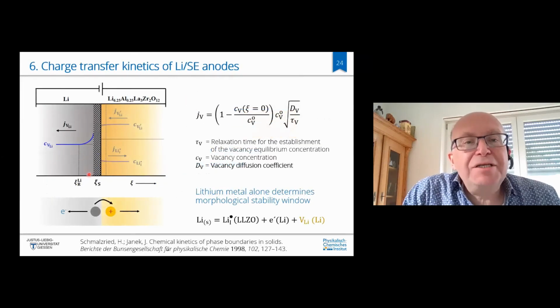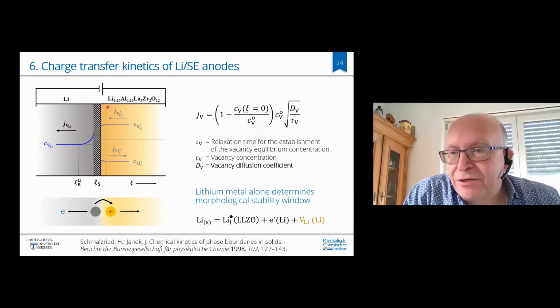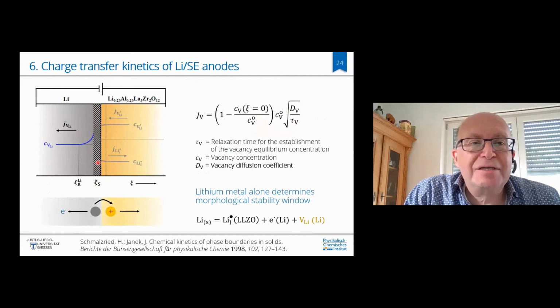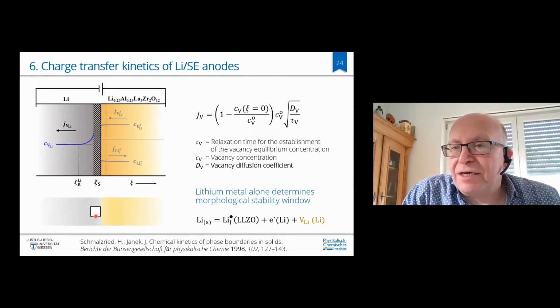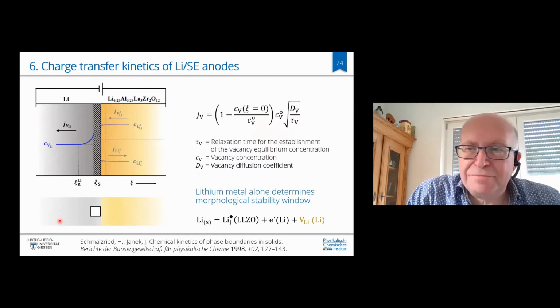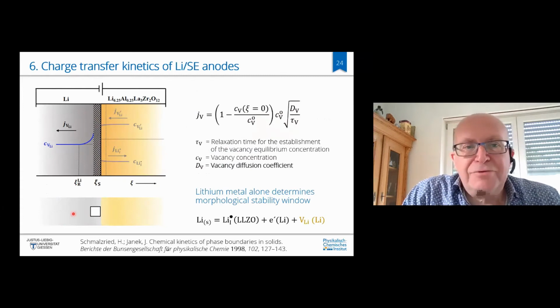Now, the critical issue of the lithium metal anode on a real solid electrolyte that has a certain rigidity is the fact that if you anodize a metal, always unavoidably, this is an inherent step, you anodize the metal, and by removing a metal atom from the metal into the solid electrolyte, a vacancy is being formed. So stripping metal on a solid electrolyte means you inject vacancies. And then the question is, where do these vacancies go? Are they fast enough to diffuse away? Then your electrode remains stable.